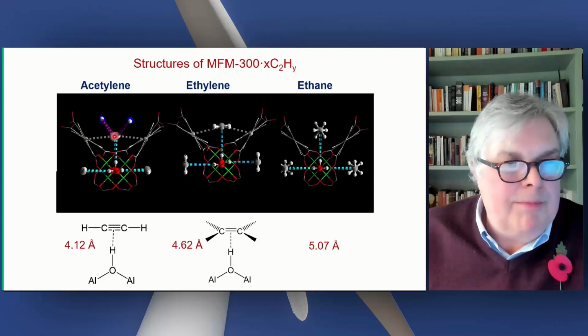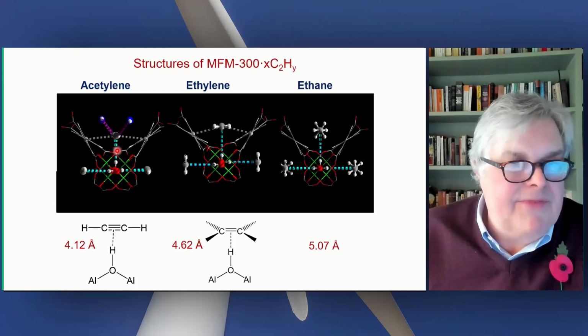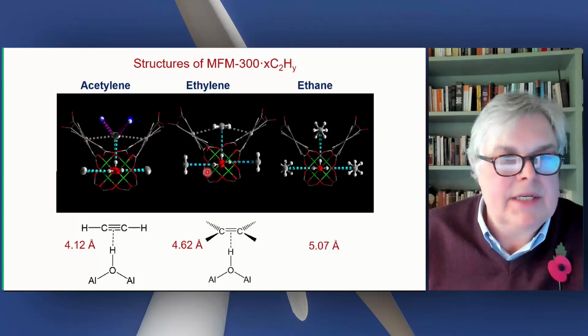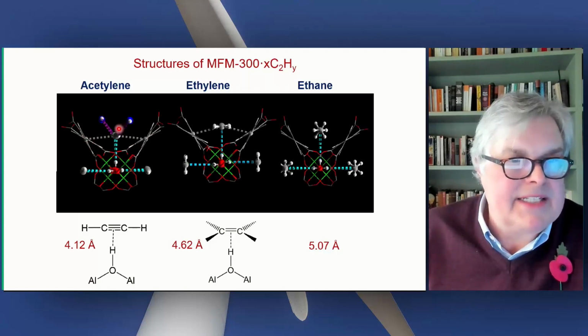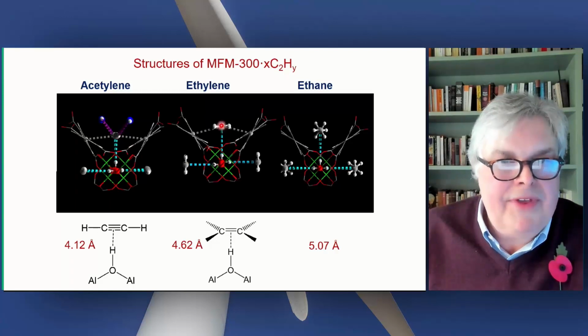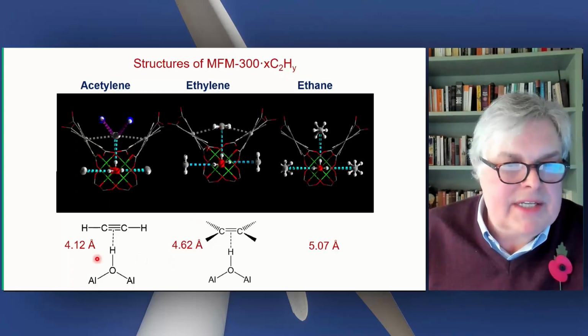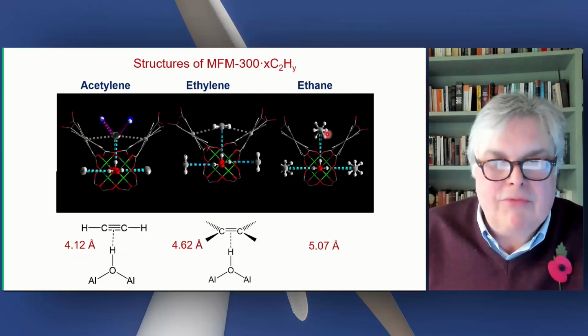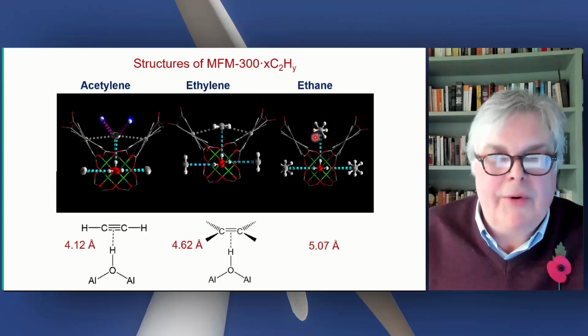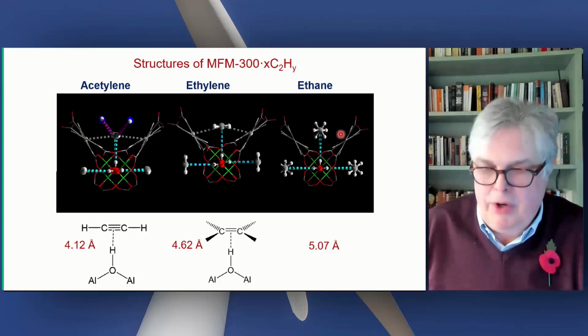Acetylene is bound more tightly. That fits very nicely with the selectivity for acetylene via this OH interaction that I think is becoming quite familiar to you. And of course, there are a whole range of other interactions taking place, including acetylene-acetylene interactions. Ethane is here. The distance is somewhat elongated compared with acetylene, and ethane really doesn't interact here. It's sitting there because that's the only place it can go. It's sitting inside a pocket.